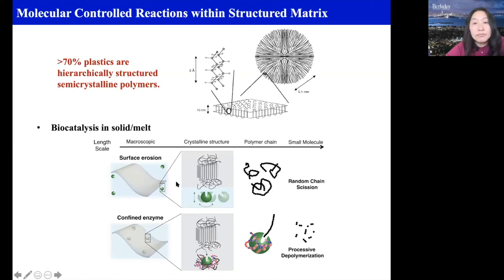catalytically active enzyme embedded in the plastic, there's different ways. And in particular, in this case, the length scale becomes important for any given polymer chain. So if we're looking at the polymer chain at the individual, at the single chain level, the dimension is typically in the range of a few nanometers or tens of nanometers. So this is also the similar size range of your enzymes. So in order for you to disperse enzyme to have access to the polymer chain, they have to disperse at the nanoscopic level. So you are basically looking at the reaction under nanoconfinement. And if you have that, and if you look into the single polymer chain conformation, this really opened up a huge playground for you to manipulate how the reaction is going to happen, what the kinetics, what is the pathway, and as well as what is your end product. Let me just give you a very quick schematic overlay.